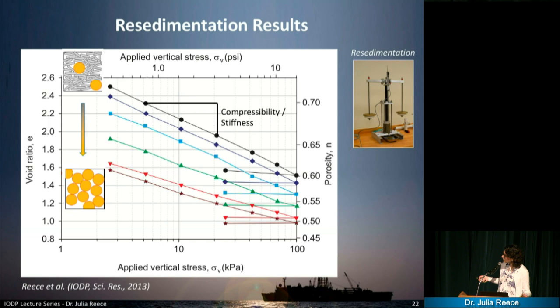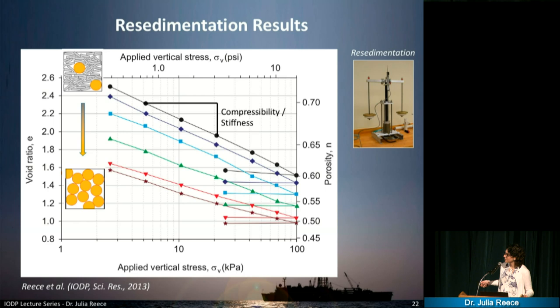The black line is the one for the pure mud that came from the Japan continental shelf. The one down here in maroon for Texas A&M is the silt that I bought off of the shelf. And then in between are the intermediate mixtures. And so what you're looking at here on the left is something called void ratio, which you may not have heard of at all. That's what the civil engineers, or geotechnical engineers use. But this is a term that is related to porosity, so to the volume of the pores in between the grains. And on the horizontal is the stress, so the stress that we applied onto these sediment samples.